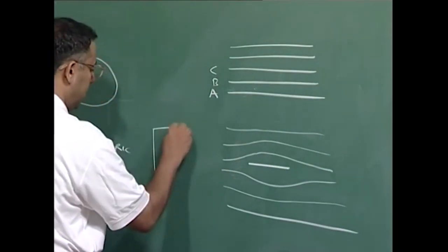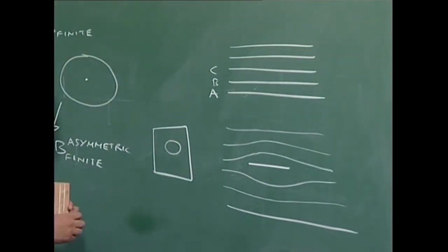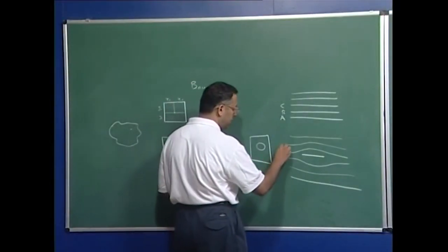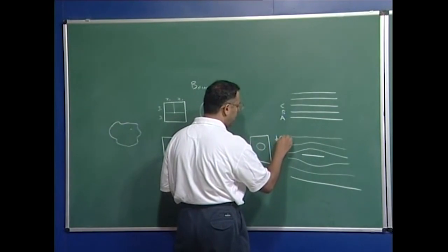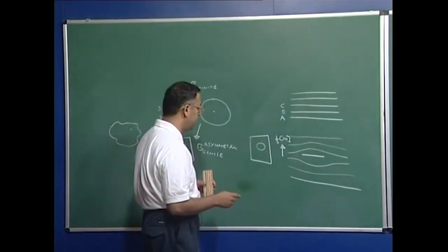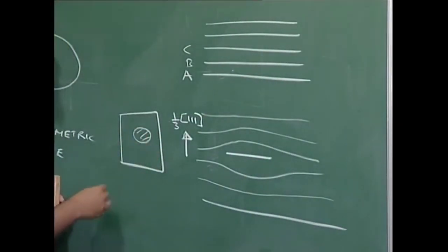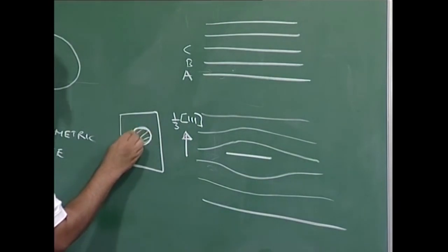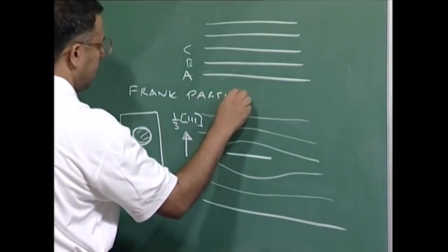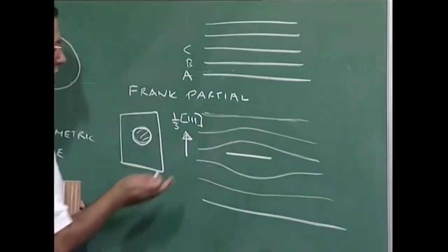Looking down on the plane, this is nothing but a disk of atoms which I have introduced inside the crystal. This kind of dislocation has a Burgers vector of 1/3 [1 1 1] type, and obviously this is not a glissile dislocation as in the case of the Shockley partials, and so this disk of atoms leads to a dislocation loop. So, the boundary of this disk of atoms is the dislocation loop, which is the Frank partial dislocation. So, these are the close pack planes viewed edge on when I am trying to understand them.